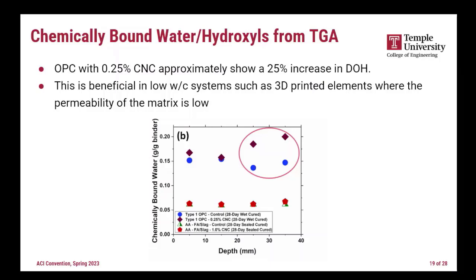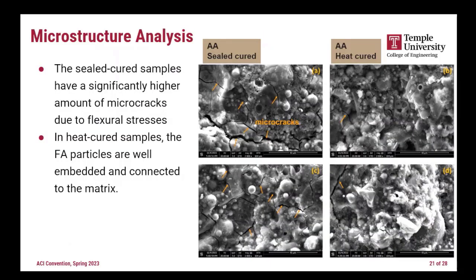But in the case of the alkali activated system, there's no impact on the reaction, which was understandable. I'm going to skip this one. We looked at the SEM images after the flexural experiment. On the left side, alkali activated seal cure; on the right side, alkali activated heat cure. You see a lot of cracking in the case of the seal cure, which makes sense, right? We have low strength for the seal cure one.